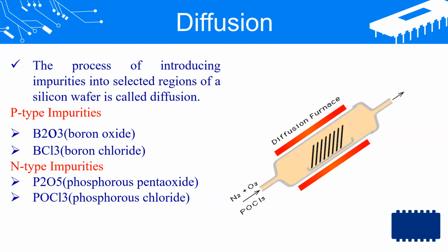The silicon wafers are stacked vertically on a movable quartz boat inside a quartz furnace tube. The temperature of the quartz furnace tube is increased with the help of resistance heaters. The dopant to be introduced is kept in a container. The dopant in liquid form, for example phosphorus chloride, may be placed inside the quartz tube in a low temperature region, or preferably outside the tube with precisely controlled temperature.